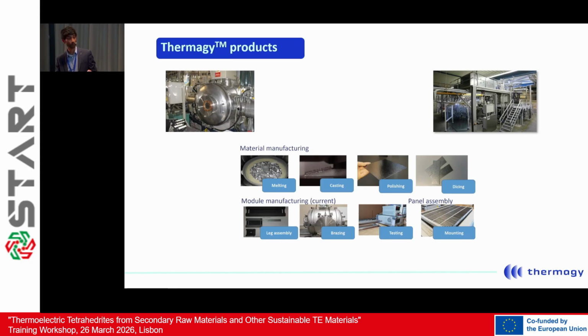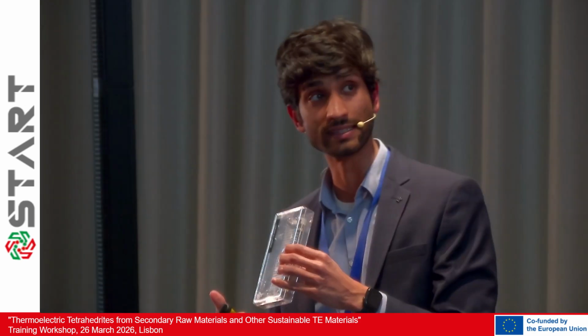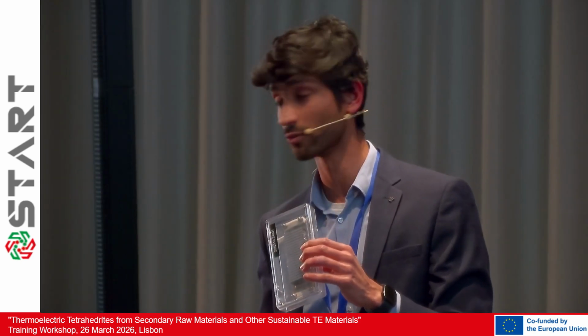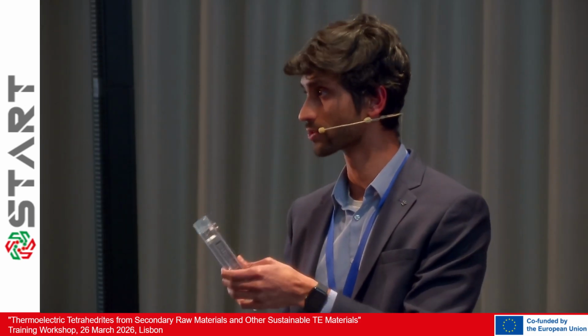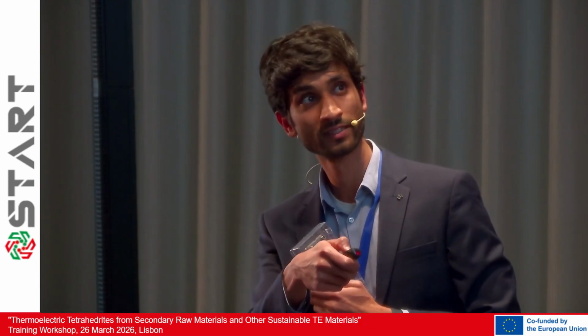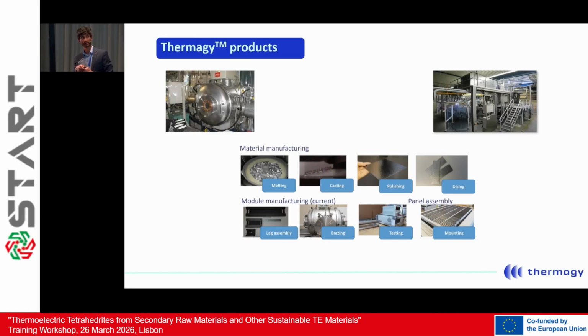This is quite important because our device now operates at 1000 degrees centigrade on the hot side. So we have to make sure that the bonding technology also survives these temperatures. That's something we had to work on for a long time, how to figure that out. And then we test each one of these devices themselves. So we go through rigorous testing, which I will show you in the next slide.